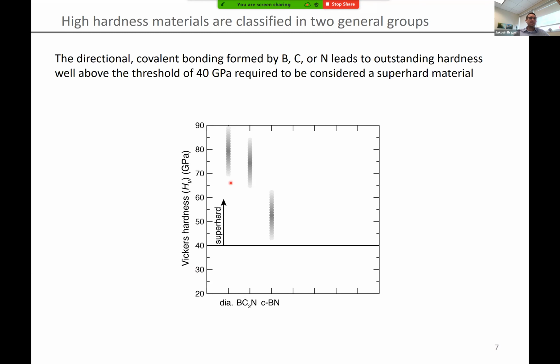You can see things like diamond have Vickers hardness ranging from 70 to 90 gigapascals. Cubic boron nitride is lower, 45 or so to 60 gigapascals. These compounds all fall above this 40 gigapascal superhard threshold - anything above 40 gigapascals is considered superhard.